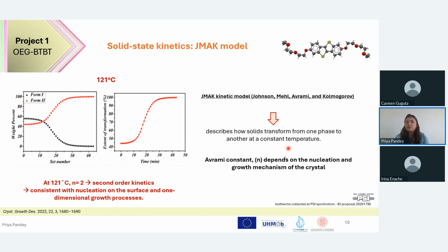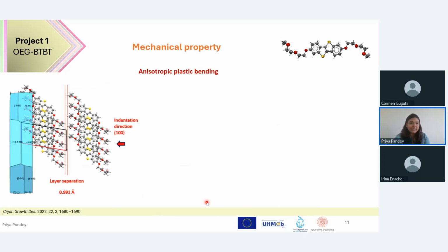So from this, we can use the Avrami equation to deduce the Avrami constant. It depends on the nucleation and growth mechanism of the crystal. For our data, I found that it follows second order kinetics, which simply means that it is consistent with nucleation on the surface and a one-dimensional growth process. I was able to do this kind of study because of the collection of the isotherms at the synchrotron, which I acknowledge. And then looking at the structure, we can also see a significant layer separation between the two layers. It can mean that this can act like a facile slip plane, which means that if we try to indent along the 100 direction, it can bend instead of breaking.